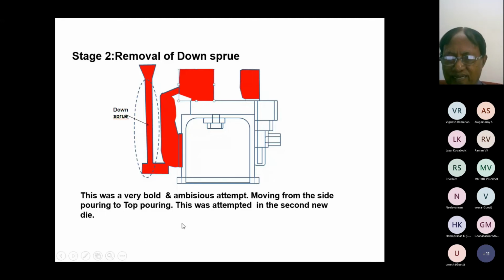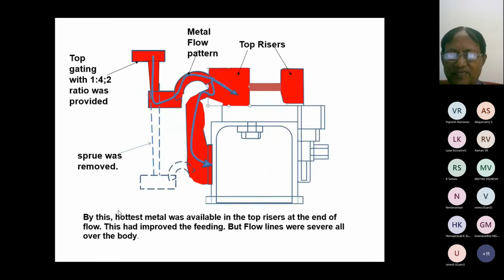This was a very bold and ambitious attempt, moving from the side gating to the top pouring. This was attempted in the second new die only, because we cannot modify the first die which is running. So we made a die and tried to block this out, remove this one and go for a gating like this, but still keeping these side risers. The metal comes here and then it falls over there and falls over there. By this, very hot metal was there in this one, and the feeding was much better.